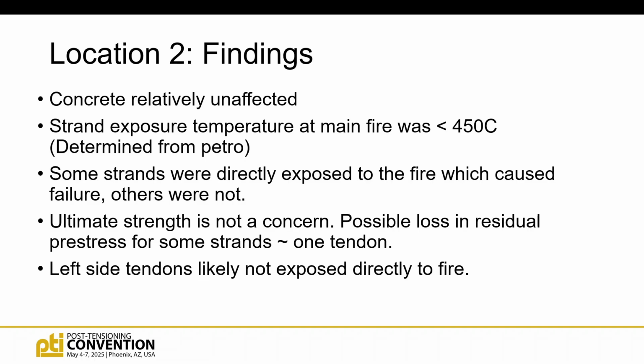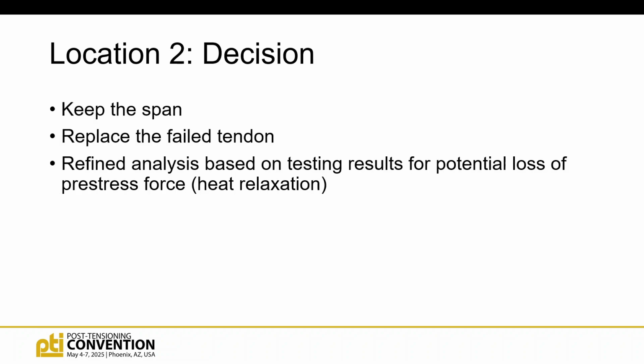and they were able to go in and redesign a new tendon with a few extra strands, because we're replacing all the anchors, and make up for the lost force with no reduction in capacity. We did consider, this was a ramp span, we did consider blocking off some of the width to reduce the traffic volume, but that turned out to be unnecessary because of our findings and Volkert's analysis. So they kept the span, they're replacing the failed tendon.